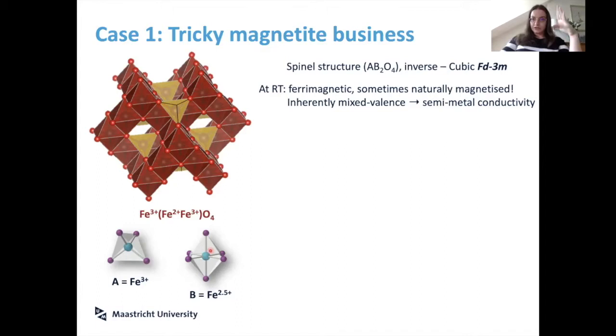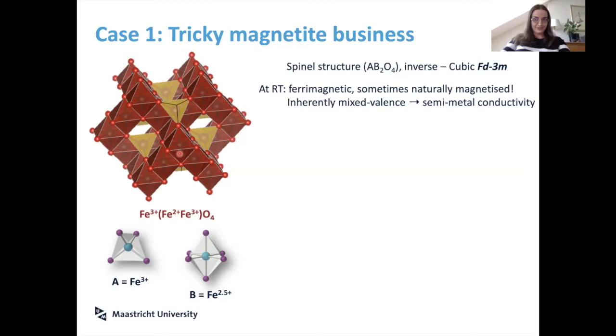Magnetite has iron in both 3+ and 2+ states sharing the octahedral position. Statistically, there must be a distribution of Fe³⁺ and Fe²⁺, which gives rise to its very strong conductivity — it's basically semi-metallic, one of the most conductive transition metal oxides you can find. It's ferrimagnetic and sometimes found as an inherently magnetized mineral, historically useful for compasses.